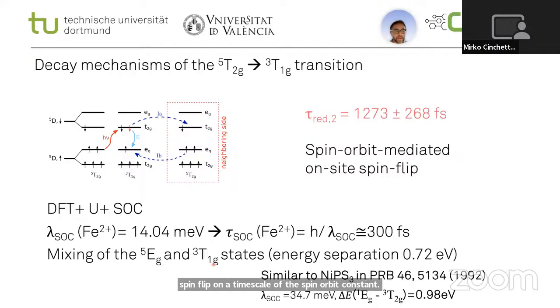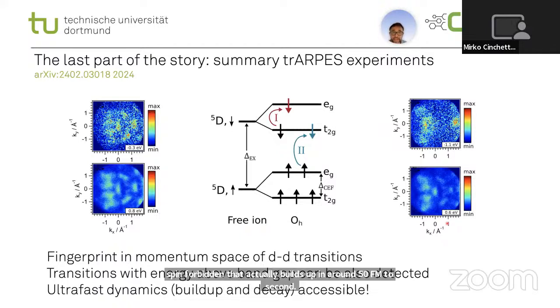Okay, so you can see that doing these time-resolved ARPES experiments gives us a lot of information about this DD transition. The last thing that we can read out of our data is that when we excite above the band gap, we have instantaneous excitation of the conduction band. And then the spin allowed and the spin forbidden transitions come with some delay with respect to the excitation, and the spin allowed transition exhibits a quicker buildup, 22 femtoseconds, compared to the spin forbidden one that builds up in around 50 femtoseconds. So I hope I showed you that time-resolved ARPES is a really nice method to get a fingerprint in momentum space of this kind of localized transition. We can detect not only the transition below the band gap, but also the one above the band gap, and we can access the ultrafast dynamics of this excitation.